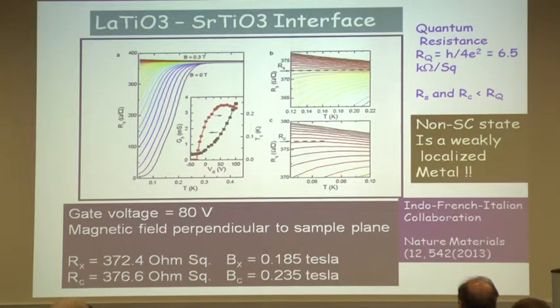And if I just blow up this section here and look at the temperature from 0.12 to 0.22, I see a region where, for a particular value of magnetic field, the sheet resistance becomes independent of temperature. This is a signature of a continuous quantum phase transition. And that critical value of magnetic field is here, and the critical value of sheet resistance is here. At this value of magnetic field and sheet resistance, the sheet resistance becomes independent of temperature over that temperature window.